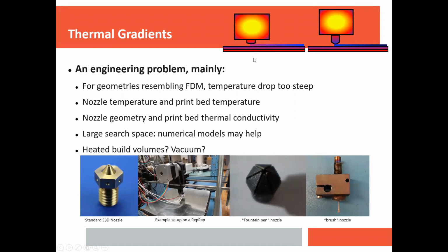Then engineering your alloy and engineering your print bed temperature and your heater temperature in the nozzle. Because you want your heater temperature and your print bed temperature to be related to the solidus and liquidus of the semi-solid alloy that you're printing. So that's a lot of parameters potentially to explore, and that's a large search space. So it just requires fast iteration. Luckily, with something that's compatible with FDM 3D printing, you can iterate relatively quickly for relatively cheap. So it's certainly doable. There's been many iterations here.